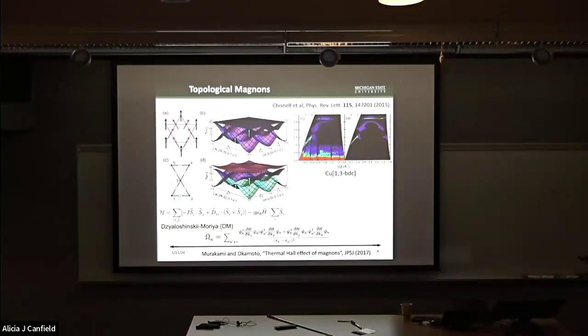The left figure is the inelastic neutron scattering data, and the right figure is the simulation results based on this Hamiltonian, where the second term here is the DM interaction. Overall, we can see that they agree nicely with each other. Particularly, if we take a close look, you can see that there's a gap that occurs at the K point. Through such a comparison, it was argued that the magnon excitation of this system is topological.